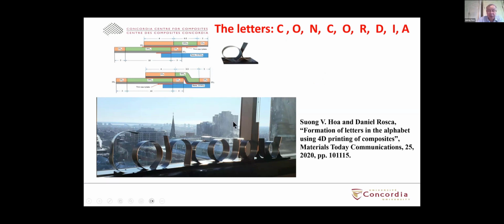Concordia, that means you're going to have the letters C-O-N-C-O-R-D-I-A. Each of the letters has some kind of curvature, but we only use a flat mold to make them. Here I showed you the configuration to make the letter A. For the letter A, this is the layup sequence. These are made mainly on the flat mold, and by the time you finish curing and cooling, it curves up to give you the shape of the letter A. So basically, that is the technique that we use.